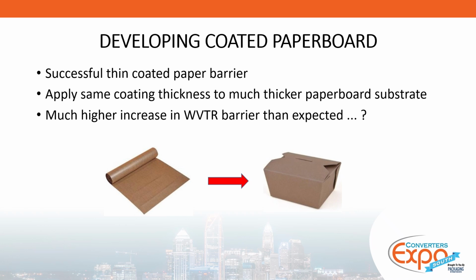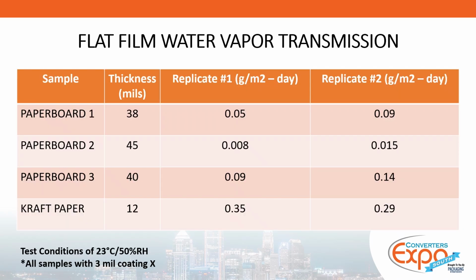So they had a successful product, and they applied that same coating thickness to a much thicker paperboard substrate. They did some preliminary water vapor transmission rate studies and found that the coated paperboard with a much thicker substrate actually increased in barrier, and it increased in barrier substantially. So they are left scratching their heads like, okay, what's going on? We know that we have a decent barrier here, but why is it so much better when it's applied to a thicker substrate? So here are those preliminary results from some water vapor transmission rate studies at 23 degrees C and 50% relative humidity. So they all have the same coating thickness, same coating process. It's just the overall thickness is different because of the substrate thickness.